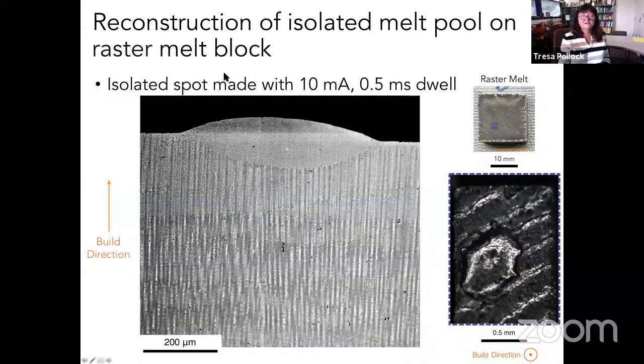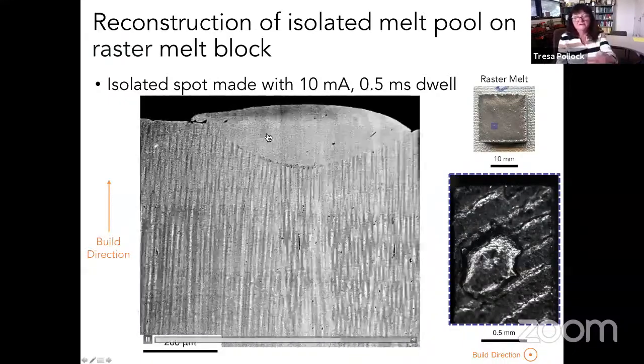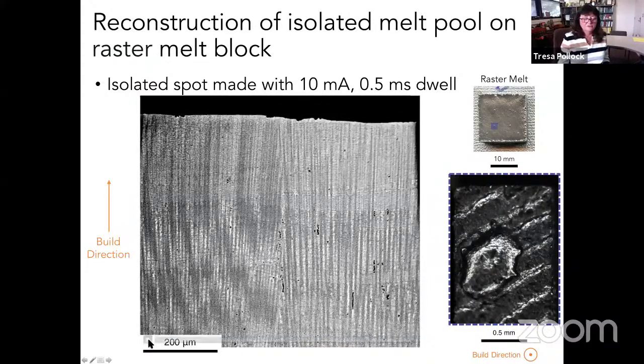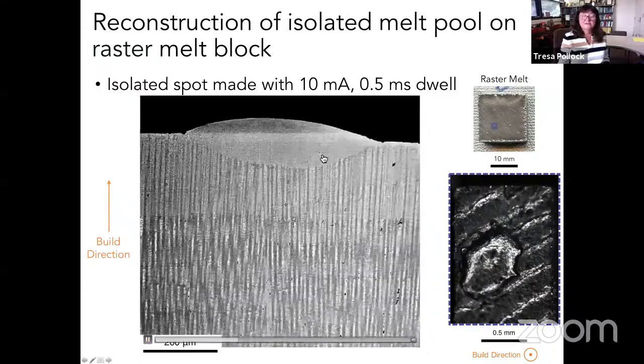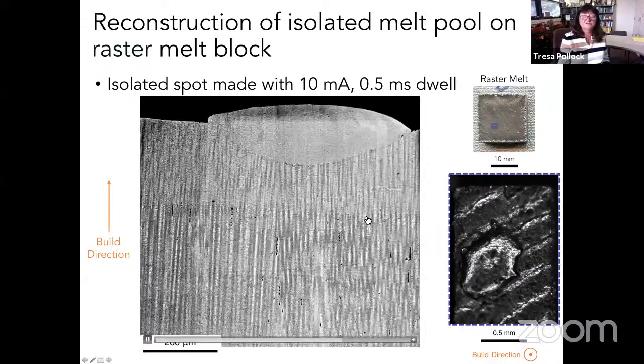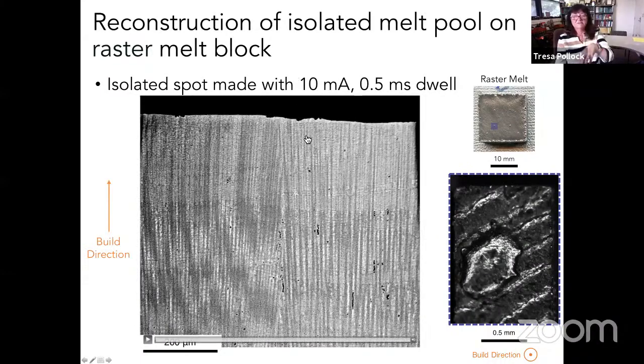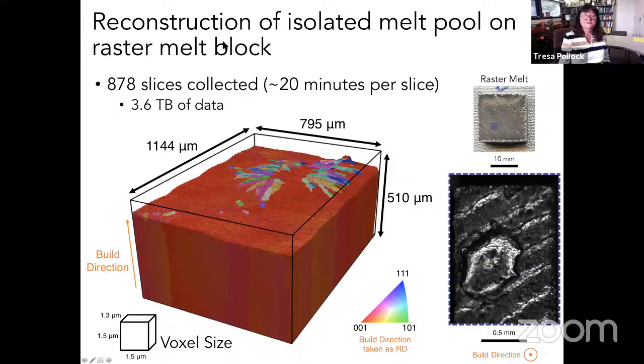Okay, so here is the isolated spot melt. And what you're seeing are slices of the tri-beam data set. And if you look closely here, you can see where the melt pool is because the structure changes as we deposit this spot melt at the top. Looking top down, this is what that region looks like that we just sectioned through. I make the point here that we have a raster in the background with the spot melt on top. And so what one can see in this 3D data set is that this raster melt that we use to get to steady state develops a strongly columnar structure.